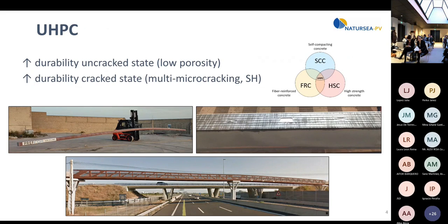Well, up to now, one of the most promising materials we have experienced is ultra high performance concrete. This is a type of concrete, as you can see in the name, which has a higher performance, not only higher strength, but higher performance in a wide sense. In the case of the sea, the most relevant is not particularly that it has more compressive or flexural strength, but mainly the durability. The durability in uncracked state comes basically from the low water binder ratio and the high capacity of the binders of the components. But also the durability in cracked state, because the fiber content is so high that when the material is cracking, you don't experience a large crack where the chlorides, the water and the oxygen will penetrate, but many micro cracks that are really more durable than a single macro crack.